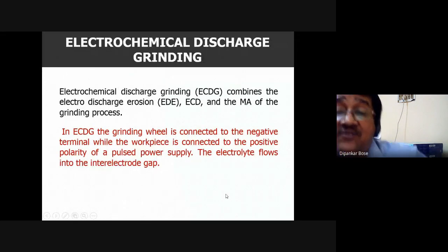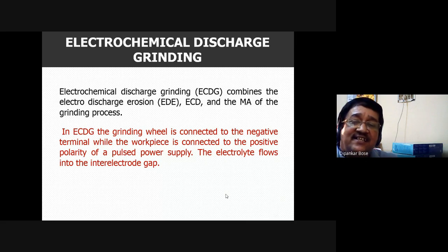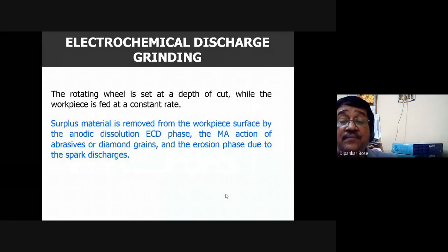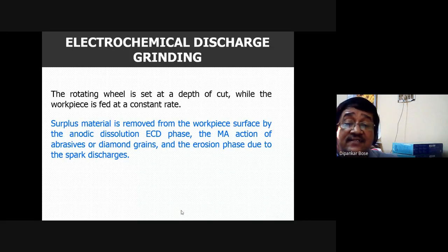Now, electrochemical discharge grinding. This is also another methodology, my dear friend. It is known as ECDG. It combines electrodischarge erosion, ECD, and mechanical action. Here in ECDG, the grinding wheel is connected to the negative terminal while the workpiece is connected to the positive polarity of the pulse power supply, and electrolyte is flowing into the inter-electrode gap. The rotating wheel is set at a depth of cut while the workpiece is fed at a constant rate. Surplus material is removed from the workpiece surface by the anodic dissolution of the ECD phase, the mechanical action of abrasives or diamond grains, and the erosion phase due to the spark discharge.